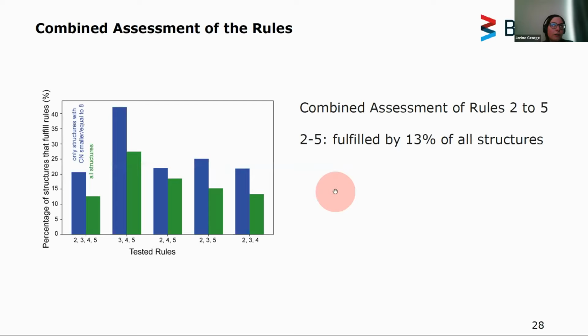And then we did a combined assessment of the rules 2 to 5 to see how well these Pauling rules are actually fulfilled by the current data that we're having. We omitted this first rule because there's really a strong dependence on the kind of radii that you're using. Depending on the radii, you might get different results. So that's why we did not include it in this overall analysis.